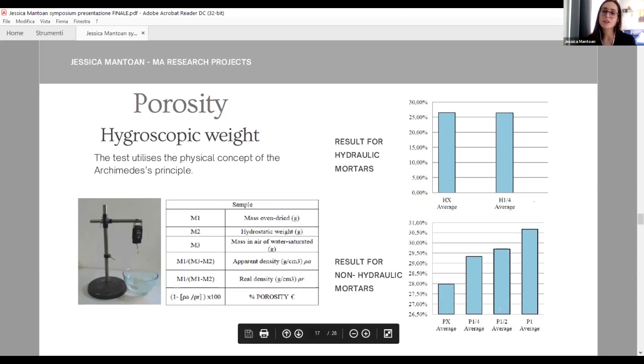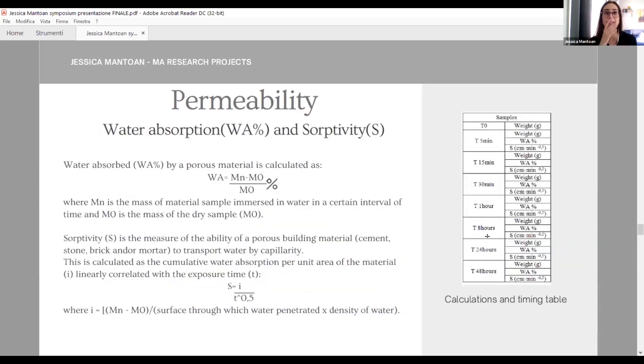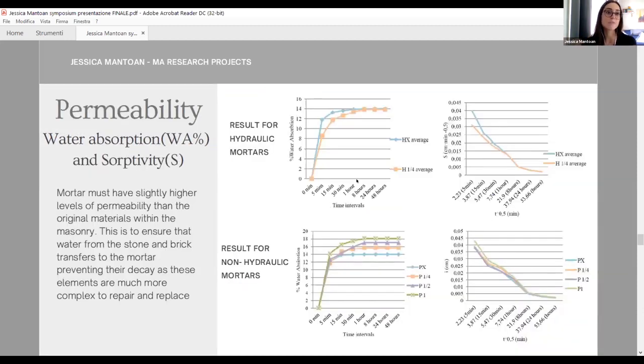But in this case, in particular for mortar presenting medium quantity of additive and mortar containing large quantity of additive, the increase of porosity is too high, and that's considered as something negative because the mortar is weak in this way. Finally, I carried out a study in permeability through the calculation of the water absorption at different timings, and the sorptivity. The sorptivity is the amount of water absorbed by a porous material just through the pores, just through the capillaries, so the really small pores. And those results gave me an idea about how the material is able to absorb water.